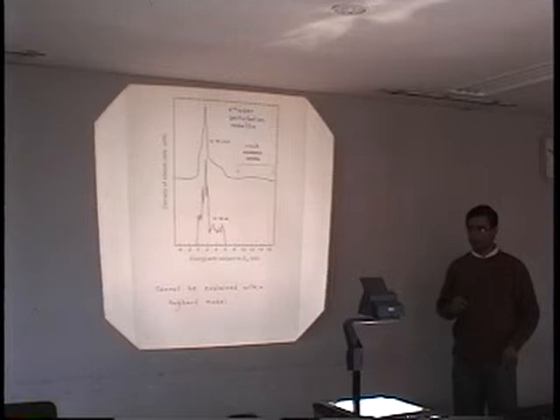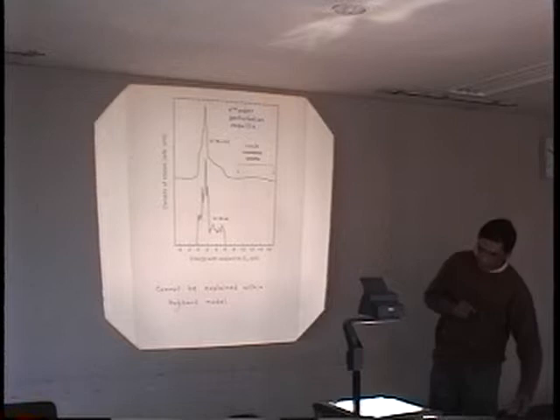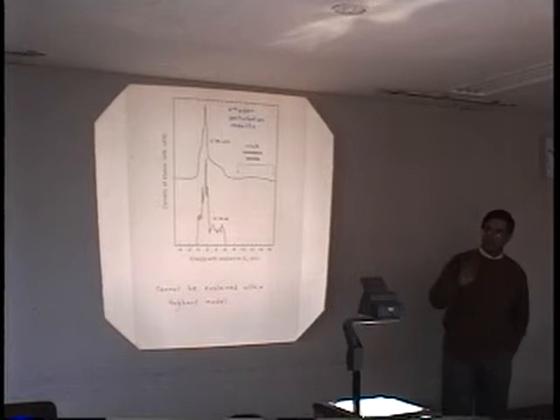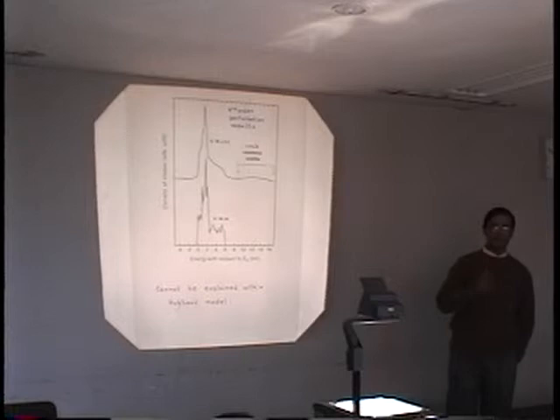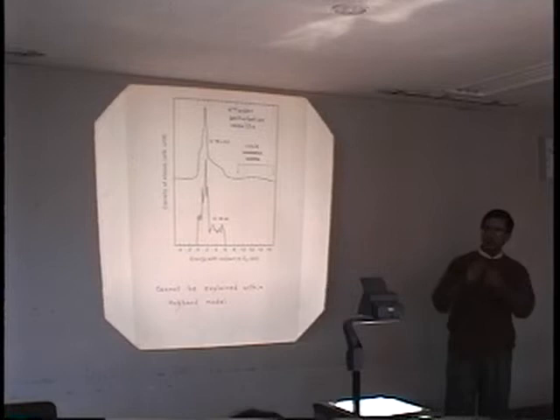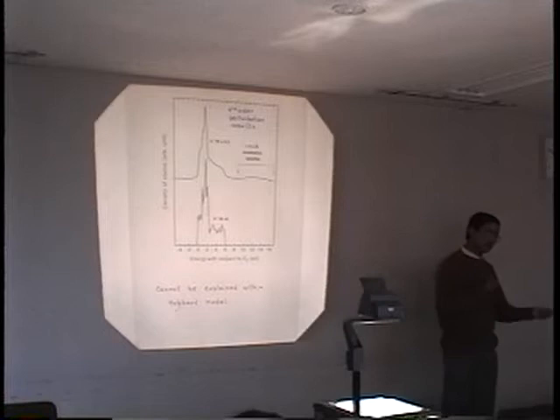Now, what is the reason inhomogeneity is coming? This is one thing that has not been realized for a long time. When we talk about electron doping or hole doping in a compound, you do not take a syringe and inject electron or holes into the compound, but you do some chemical substitution. You either pull out strontium, put in lanthanum, or pull out lanthanum, put in strontium, or you create oxygen vacancies.